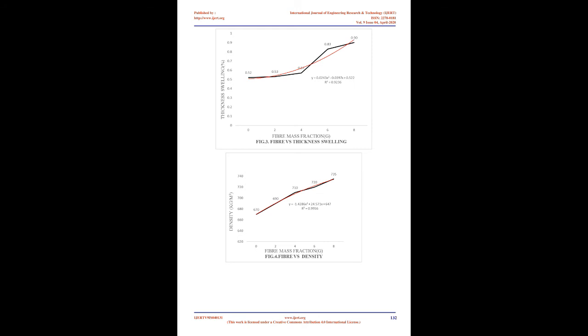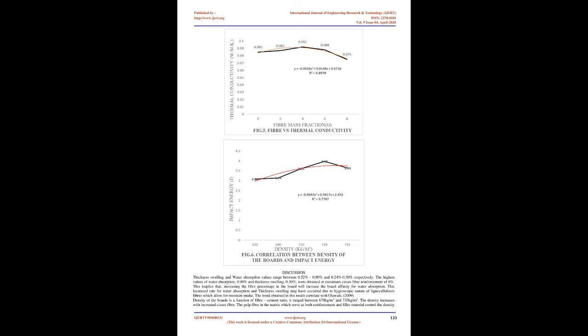Discussion. Thickness swelling and water absorption values range between 0.52%, 0.90% and 0.24%, 0.30% respectively. The highest values of water absorption, 0.90%, and thickness swelling, 0.30%, were obtained at maximum Cissus fiber reinforcement of 8%. This implies that increasing the fiber percentage in the board will increase the board's affinity for water absorption. This increased rate of water absorption and thickness swelling may have occurred due to the hygroscopic nature of lignocellulose fibers, which allow for moisture intake. The trend obtained in this result correlates with Olaoye, 2009.